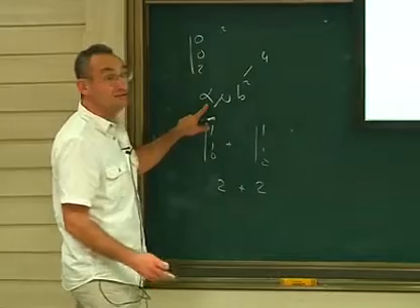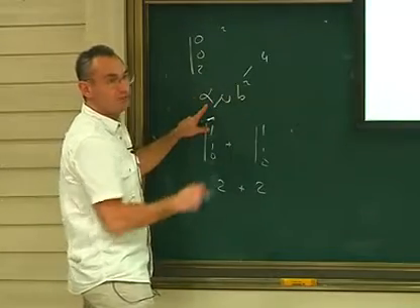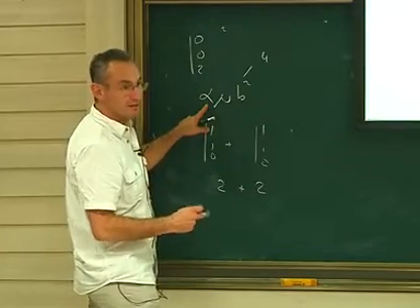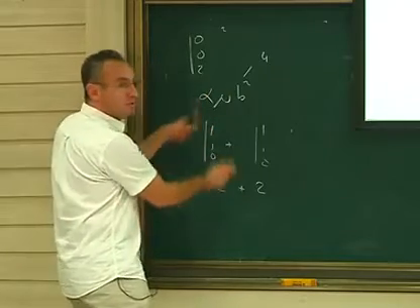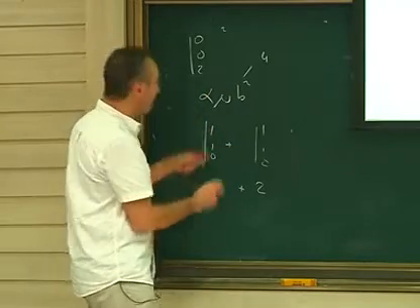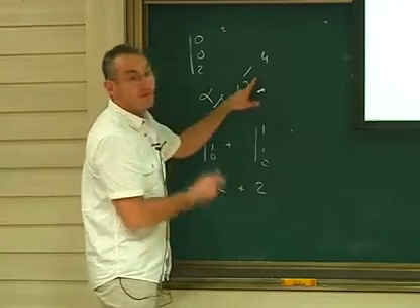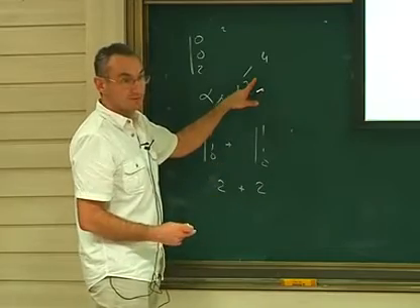But macroscopically, if we just look at that, which is wrong, when we do that, there is something which is missing, which is that alpha is not the same for each arm. You need to take into account the anisotropy of the line. Some of the part will be edge, some of the part will be more screw. Because of that, there is a small change of energy. So finally, this is favorable, but very weakly favorable.